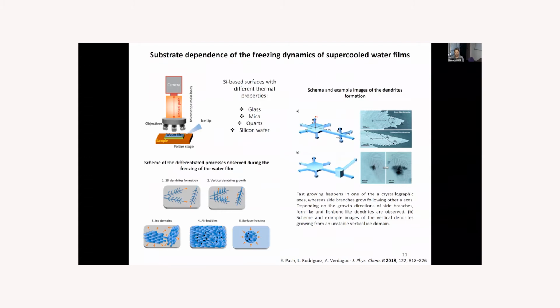So we have studied different surfaces and particles for the freezing of water. One of the studies was based on silicon-based surfaces with different thermal properties, such as glass, mica, quartz, and silicon wafer. We have studied it by optical microscopy and acquired fast films of the freezing processes. We could identify the two known processes of water freezing, which are the fast two-dimensional dendritic growth, and then the freezing of the total liquid water which is left after the dendritic growth.